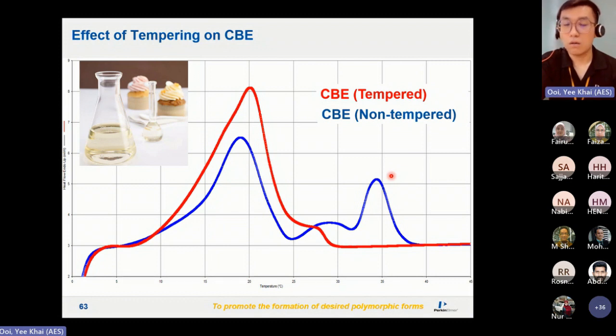Chocolates, they do not want it in this form. So they go through a tempering process, which means they temper the material under a certain temperature and then adjust the form into what they want. Usually it's the beta prime form. After tempering, they use DSC to check, okay, now this is the form that the manufacturer wants. The slogan says that the chocolate melts in your mouth, not in your hand, all because it exists in this form.